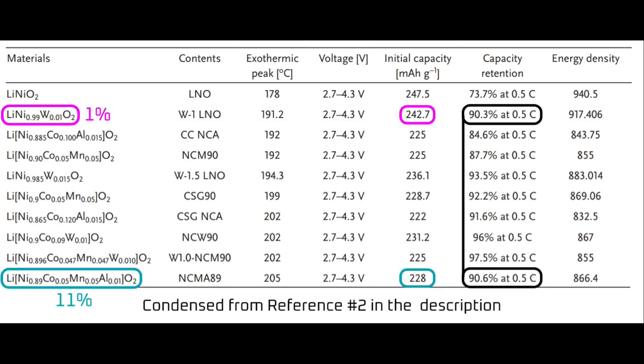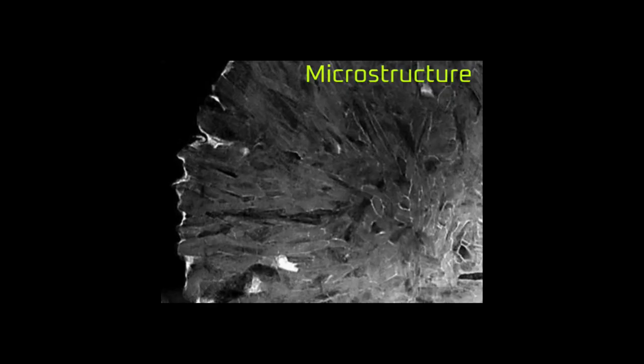For example, 1% weight of the tungsten in the cathode appears to be as potent as 10% weight of other dopants. There are two ways to use tungsten. It can be used to create a microstructure cathode where the tungsten is doped evenly throughout the crystal structure, or